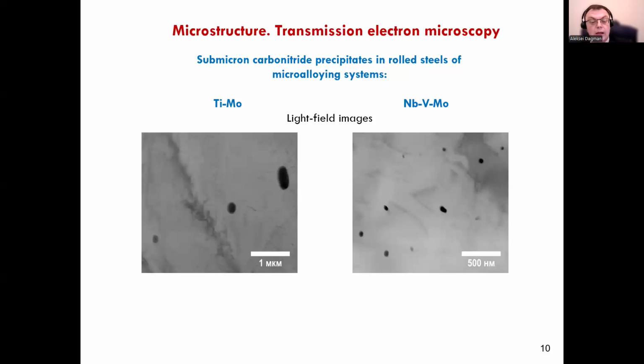In the rolled steel of the vanadium-molybdenum microalloying system, the precipitates observed were small, less than 20 to 30 nanometers. This is due to the low temperature at which, under thermodynamic conditions, the release of vanadium carbonitrides occurs compared to niobium carbonitrides. The carbide and carbonitride precipitates form at an early stage of thermal deformation. Treatment in niobium microalloyed steel increased to a greater extent, which was additionally facilitated by the higher end temperature of hot rolling.